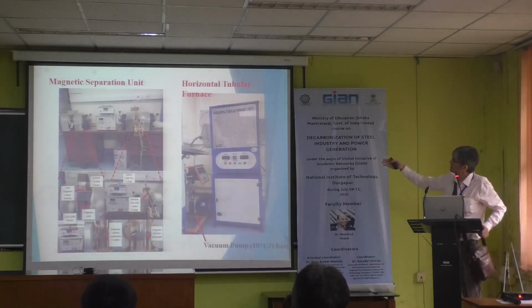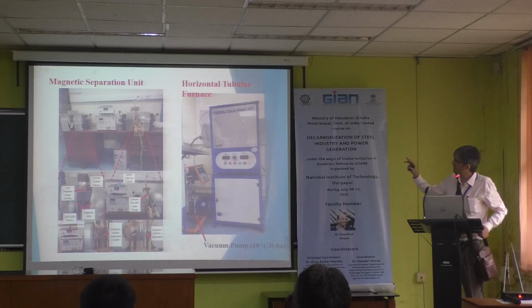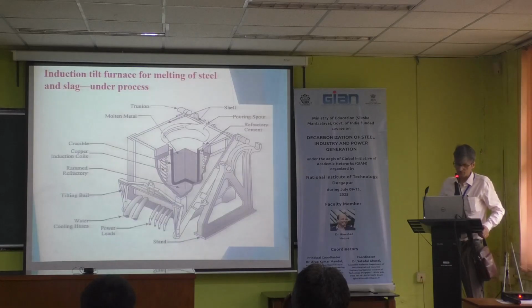These are the magnetic separation units, the Davis tube. You must be knowing about it. This is the horizontal tubular furnace, which is also assisted with vacuum. We have not used it so frequently. But here we also have a controlled atmosphere facility. That means we can control the atmosphere, but we do not have any measurement while the process goes on. But we can do it under vacuum. We can use this one also. This is a tilt induction furnace. I will show you the video of the tilt induction furnace which we have operated. We tried to melt it with blast furnace slag, and also investigated one project, dephosphorization in the induction furnace.